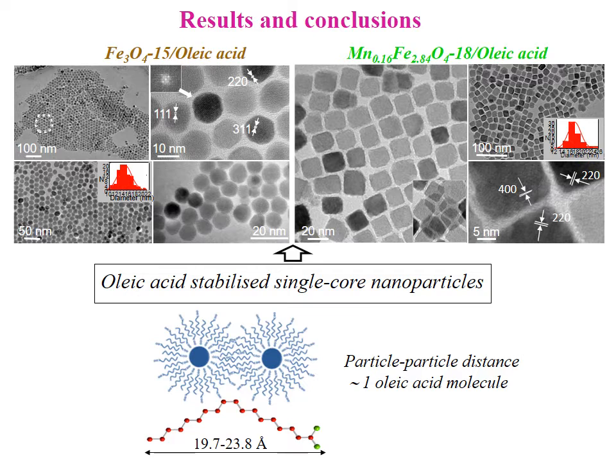By this synthesis method, magnetite spherical nanoparticles with a diameter of 15 nanometers and manganese iron nanoparticles with a major dimension of 18 nanometers have been obtained. In both cases, the particles are crystalline, as indicated by the high resolution image, the order and spacing sequences corresponding to the different crystallographic planes.